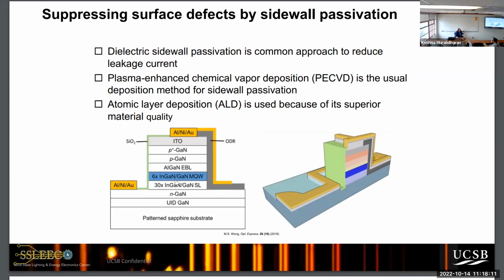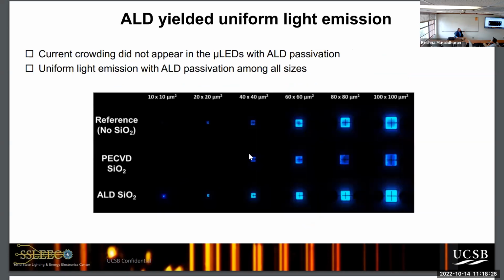And then this quantum well region where I added the indium, this is where all the light comes from. So each quantum well, by the way, is only 3 nanometers. So that's 30 angstroms. So we do 6 of those here, and this is our light emitting region. And so, like I said, this was the reference process. This is the process used in industry to make light bulbs.